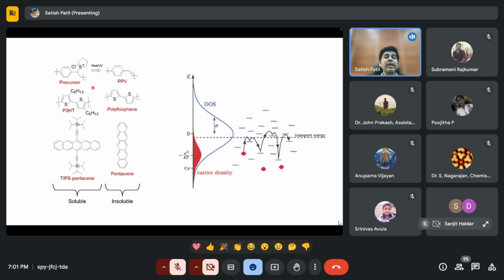So one has to be very careful about the position of these alkyl chains. For example, in the case of polythiophene, it was very cleverly introduced at the third position so that they don't inhibit the charge transport, but however increase the solubility. So organic chemistry plays a very important role here. It is not very easy to identify the positions where to introduce alkyl chains and how they participate. So rational design of these polymers is very, very important to control the charge transport and increase the solubility. So there is always a trade-off.